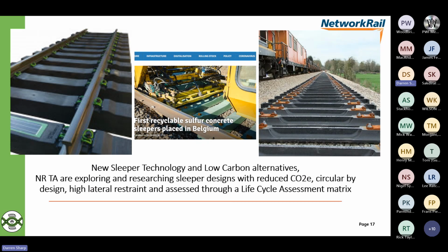In the centre there is a sulphur sleeper, so this has been decided to be taken on, and a colleague in TA is actually trialling the sleepers in the next 6 months, and that uses sulphur in place of cement in the mix, and it's fully recyclable as well. So you can heat the sleeper up and basically remold the sleeper using the same materials, so fully recyclable and circular. The right hand side is another plastic sleeper, uses less plastic, but as you can see, its shape beds into the ballast, so it provides increased lateral resistance, and works better with the ballast as well, and reduces the ballast degradation.